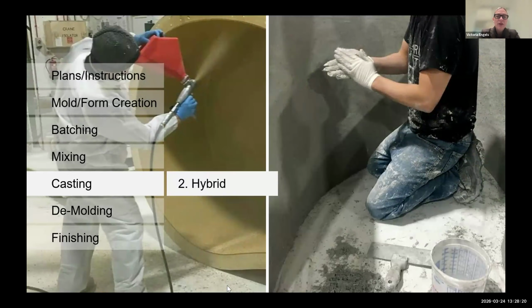A second method is a hybrid or spray and lay process. This is a two-layer method. The first layer or face coat is a thin surface layer sprayed with a gun directly into the form. A backer layer of GFRC, a thicker mix that contains glass fibers, is then added behind the skin in order to provide strength and achieve the overall desired thickness. This backer coat is either poured in or hand-packed, as seen in the image on the right. Hand-packed GFRC is thick enough to be sculpted and is often used on pieces with vertical surfaces because it can retain its shape against gravity.